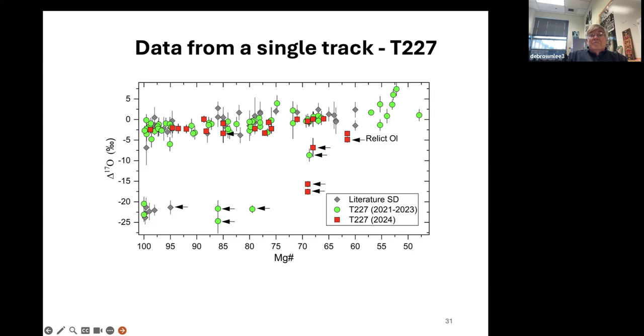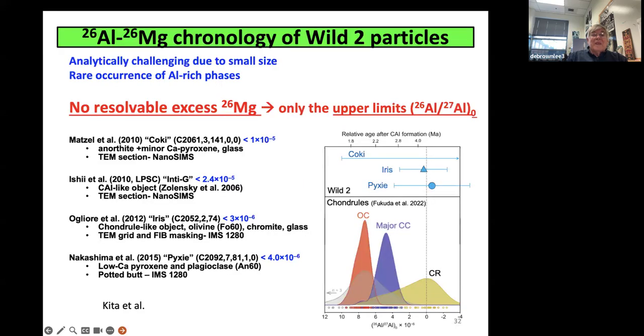Here's the data from many particles from a single track that we have, and these are all grains that are larger than 5 microns in size. We've got over 100 points now, and you can see again there is a positive slope. There's this interesting thing at the far right-hand side, the iron rich, low magnesium number, high iron, which is actually with cap delta positive values, meaning above the terrestrial fractionation line.